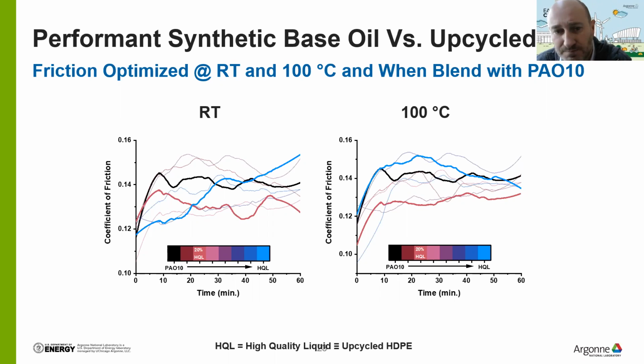We did both at room temperature, but also at temperatures like when you turn on your car, you're at room temperature, or depending on where you live, in Chicago, it can be freezing. But also at 100 degrees, which is roughly the temperature a car engine reaches after a couple of miles. And we show, for example, that at roughly 20% weight loading of liquids from plastic waste added to a polyalpha olefin 10, we have an improvement of the tribological properties. And now we are trying to understand why there are these improvements. But this is also a good way that you could, for example, blend synthetic oil with plastic waste.